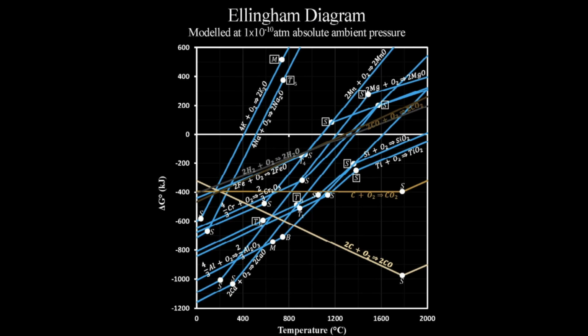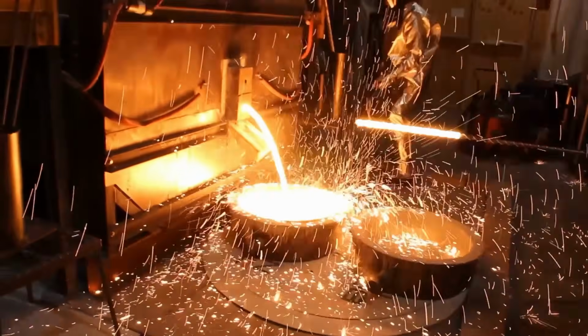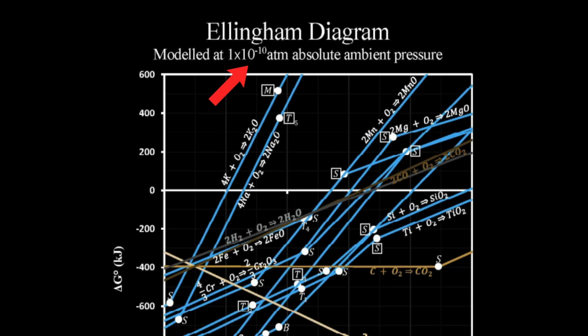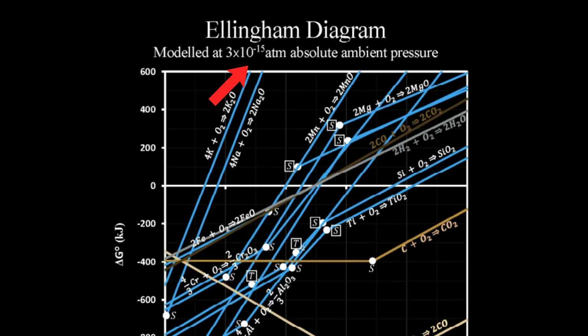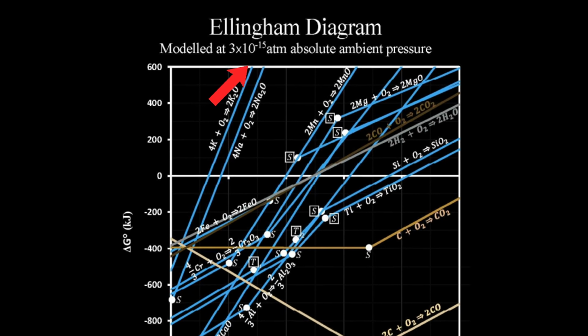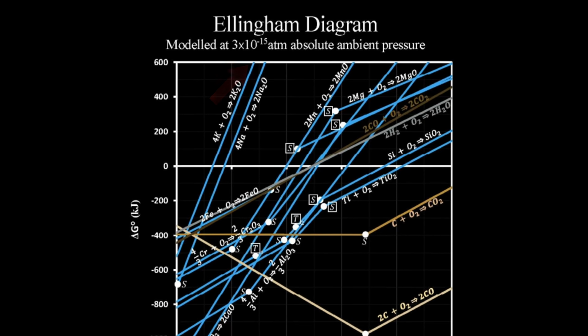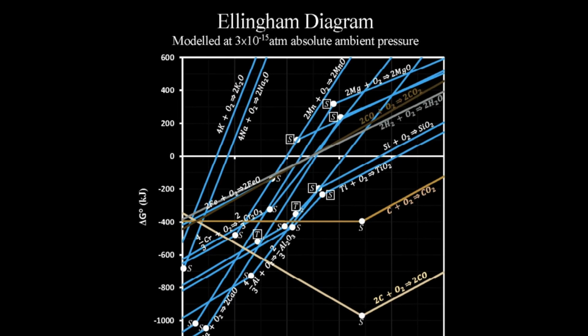And look, nearly every oxide sublimates or boils completely around 1400 degrees. Iron around 1100. This is just absolutely insane when you realize our original electrolysis process, like the one employed by Lunar Resources and Boston Metals, has an operating temp of 1600 degrees. And this isn't even the lowest vacuum diagram. This is 10 to the power of negative 10 atmospheres, while this chart, 10 to the negative 15, represents the pristine lunar environment. So the sublimation temperatures can actually be even lower.